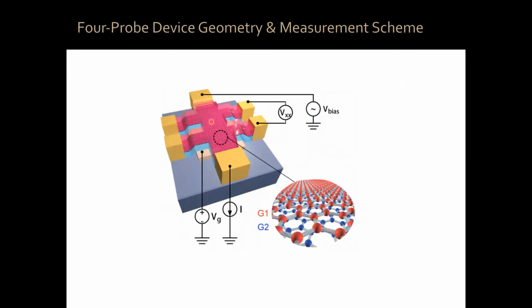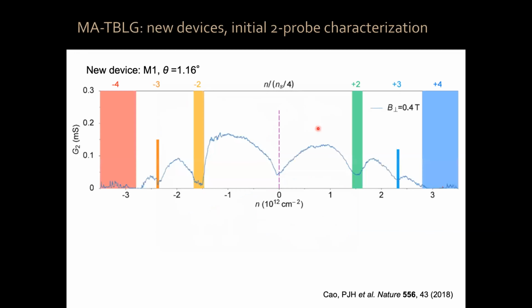Okay, same type of fabrication, graphene on graphene with a small angle. And now we can have source and drain electrodes and independent voltage measurement probes so that we can measure within the graphene and see if there is any resistance there at all, okay? And this is data for another device. This is 1.16 degrees. These are the data with a small perpendicular magnetic field applied to it. You can see these are also data in 2-terminal conductance so that we can first characterize them in a 2-terminal conductance because it's simpler, okay?